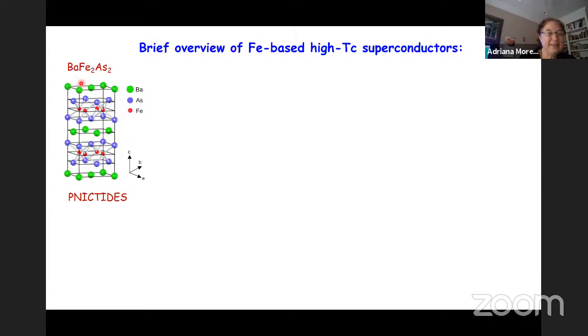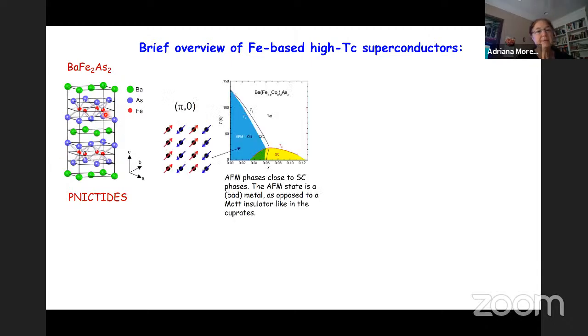These are materials that have planes of iron with a pnictide either above or below the planes. The irons form a square lattice, and at the center of the plaquettes, either above or below, we have a pnictide. These are the planes. These materials, when undoped, have magnetic order. The magnetic order is of the form (pi, 0): antiferromagnetic in one direction, ferromagnetic in the other.